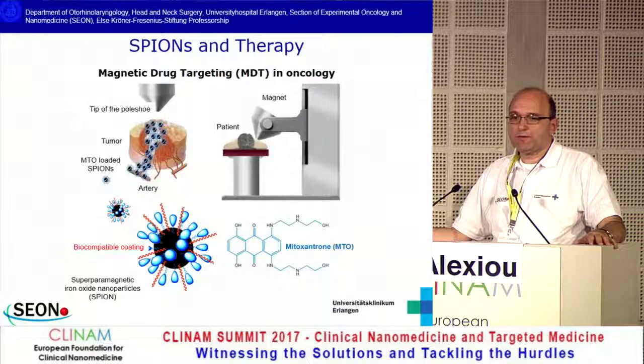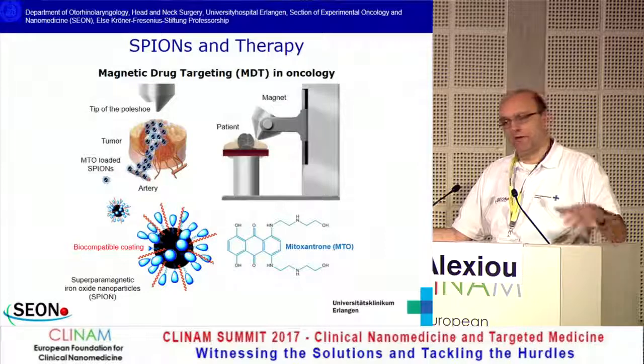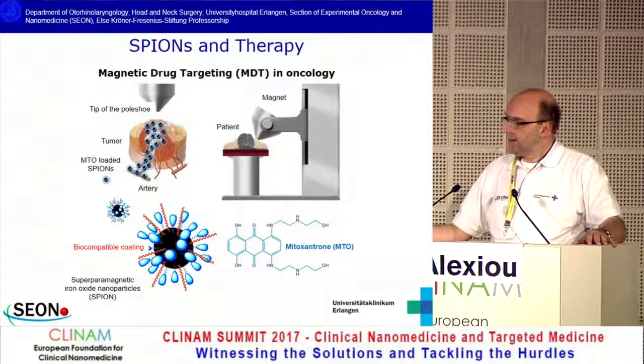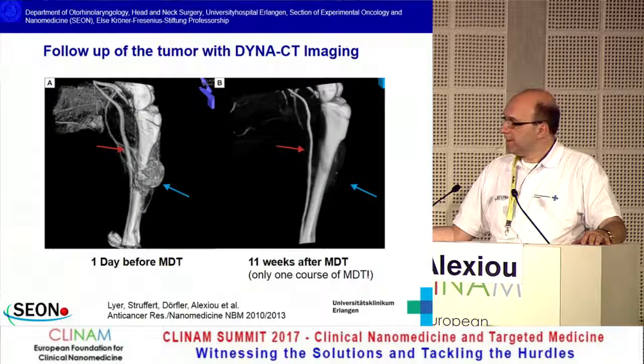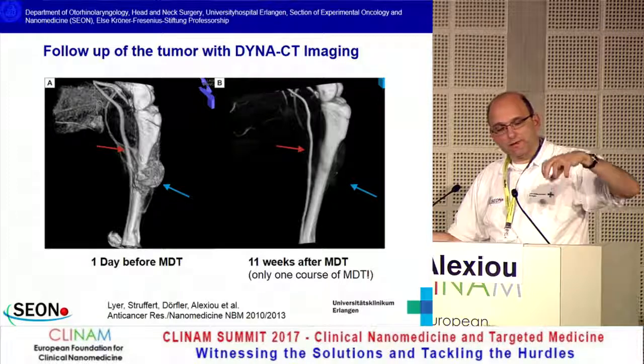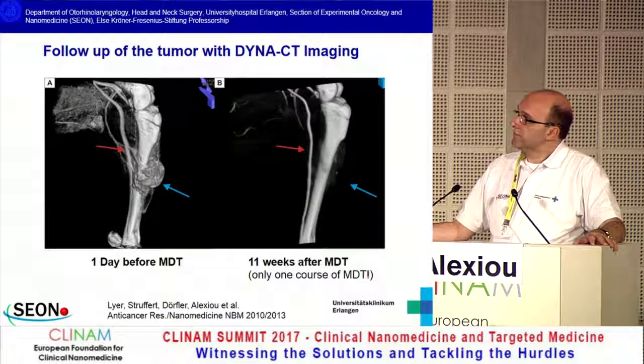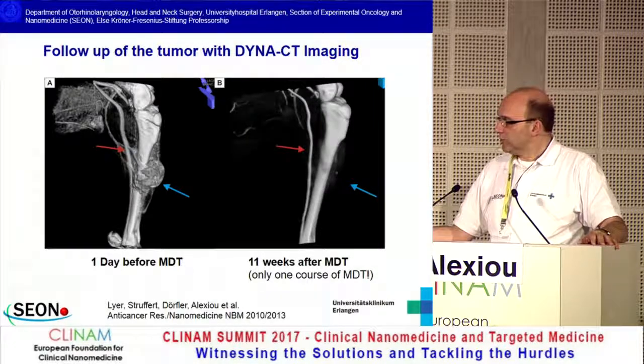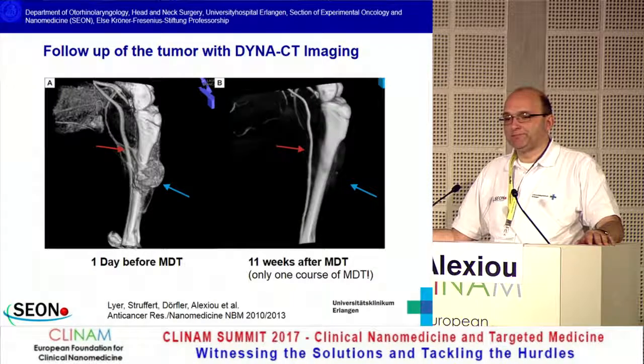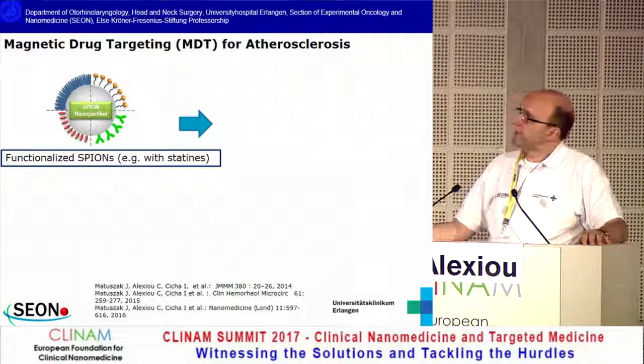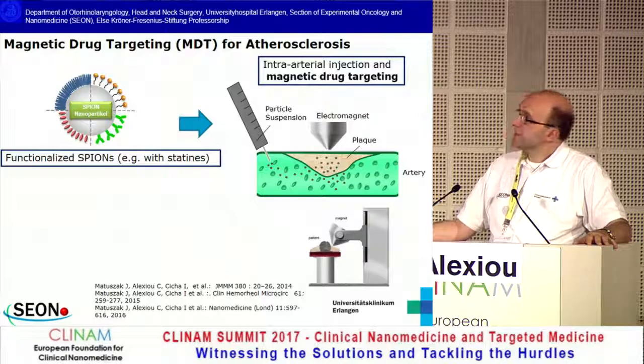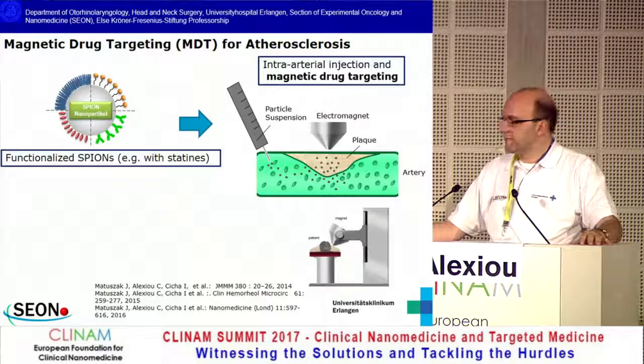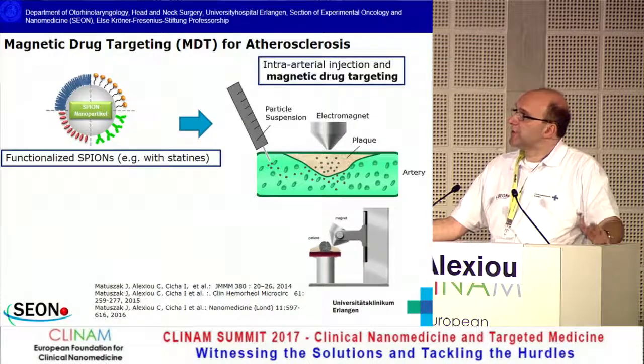Another part, as mentioned, is therapy. What we are doing in our lab is magnetic drug targeting — specific delivery of a chemotherapeutic agent guided after intra-arterial application in animals, directed via an external magnetic field. We gained complete tumor remission after one course: particles with chemotherapeutic agent concentrated in the tumor tissue, and we have complete tumor remission in these animal groups after at least 11 weeks. Within our European funding NanoAthero, together with Didier Letournier, we also apply magnetic drug targeting for plaques, using iron oxide nanoparticles bound to statins.